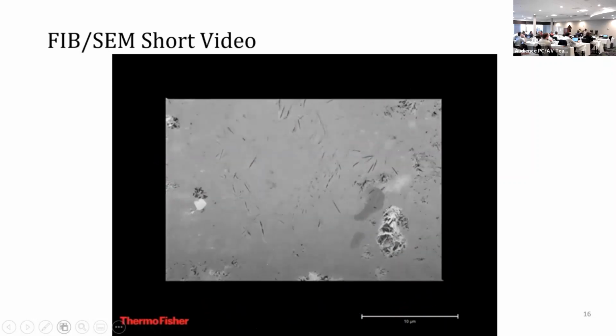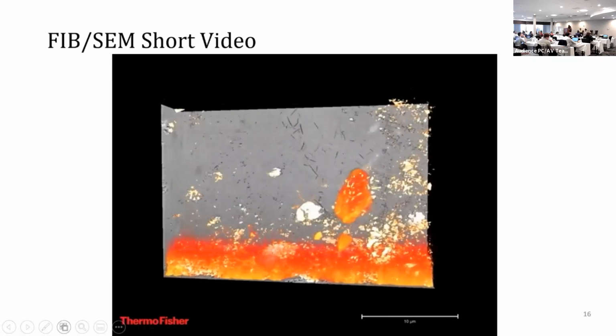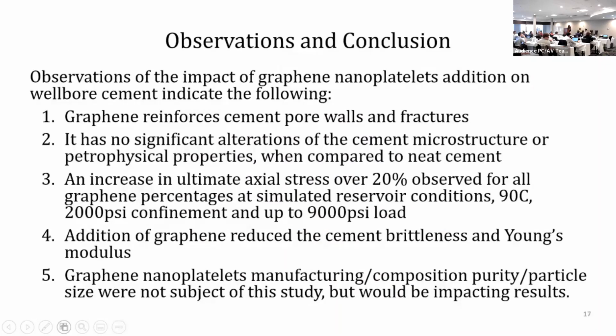What are the major observations from this? We see the graphene reinforces cement pore walls and microfractures. We don't see a major change in the CSH shape, because that cannot be obtained from looking at cement. You really need to do that with graphene in a C3S type of slurry.